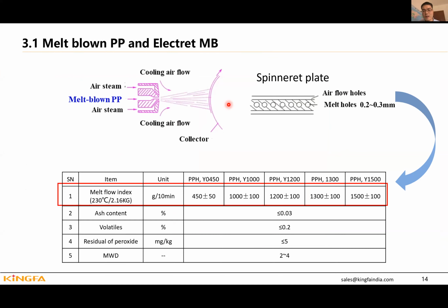The PP melt comes into the die, and in the die they have a spinneret plate. In this plate, they have thousands of small holes. The dimension of each hole is only 0.2 or 0.3 millimeter. So the PP melt comes from this hole and then is extended into fiber by the hot air.